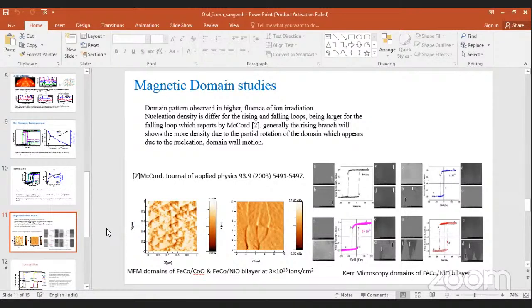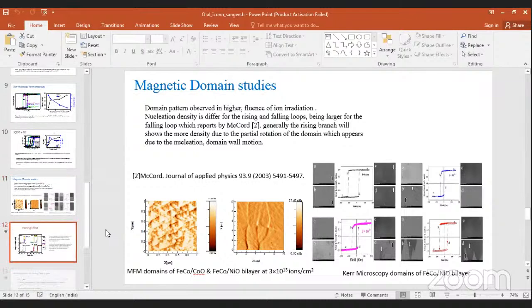Moreover, in the magnetic studies, the domains are present in the initial state, that's without the irradiation, and those are nucleated in the pristine state. After the irradiation, domain wall motion has appeared.